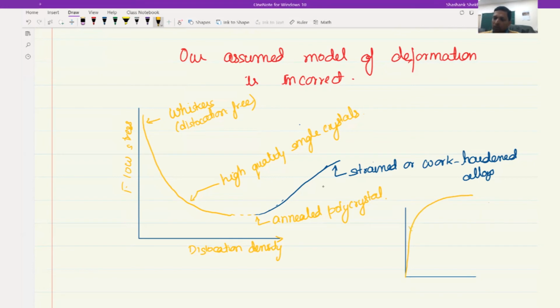So somewhere over here, we have plastic deformation that begins. And as you keep increasing strain, we see that the flow stress required is higher and higher, which is also expressed by the power law hardening relation, which clearly shows that as strain increases, flow stress increases. But if it were just a shearing of the planes, why should the flow stress increase? It doesn't make sense. Therefore, again, this emphasized to Taylor that there must be something more than we understand.